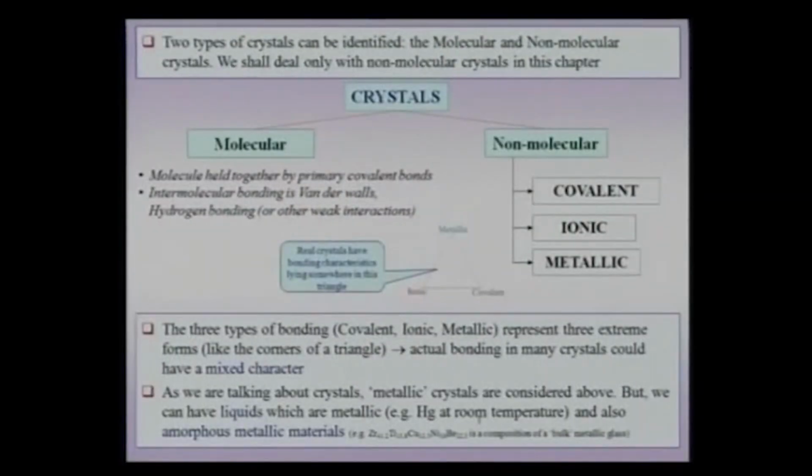That means that if I take a composition like this, melt it and pour it into a copper mold, I can get a glassy material. Of course, I will not make the copper mold too thick, I would like to make it somewhat thin so that the walls nearby can extract my heat, but still these materials can easily be glassified or made into a bulk amorphous alloy.